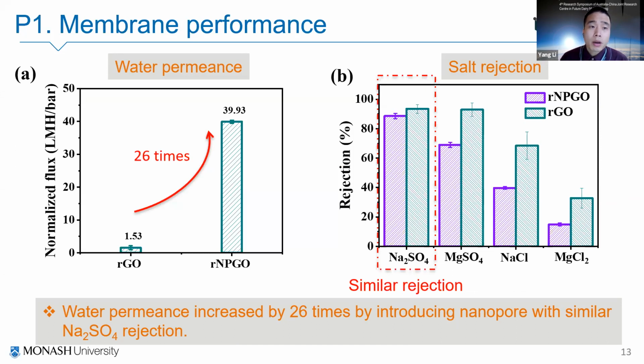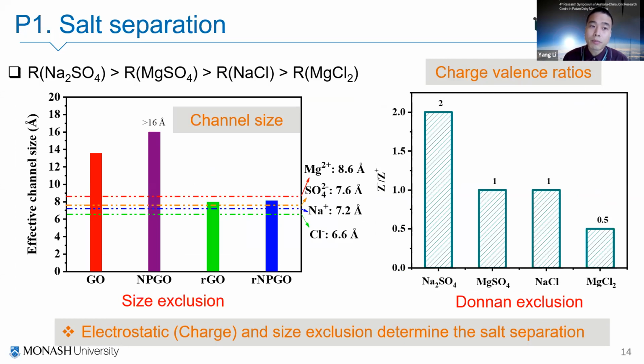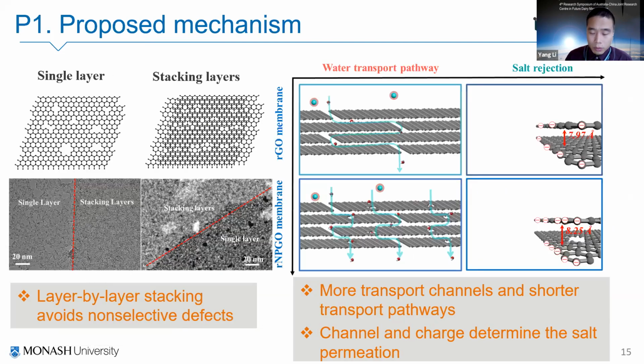This result is very promising. When we go deeper into the mechanism, we found that the salt separation is dominated by the charge properties, which come from the negative charge functional groups on the membrane. Another thing is the size sieving effect. The channel size when in water is around 1 nanometer, which is very close to the sulfate ions. So the mechanism of the nanopore introduction into the membrane is that by layer stacking, the nanoporous laminar membrane has additional transport pathways, and the charge and the size sieving effect enable the membrane to be applicable for nanofiltration applications.